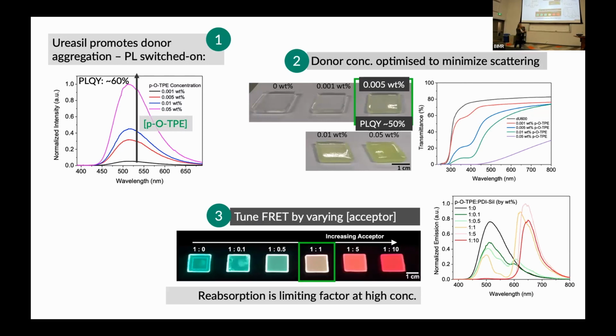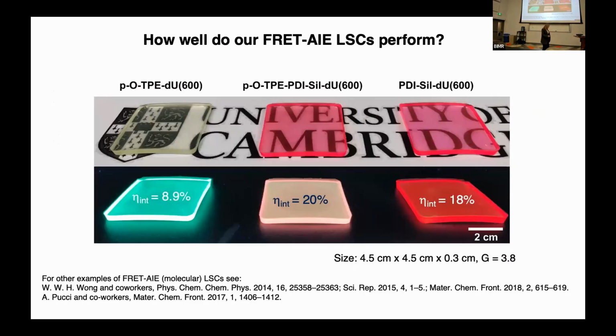So coincidentally, we found that a 1-to-1 ratio of the donor to acceptor worked best. That was just how it worked out. So what we did is we made big LSCs, and we looked at the internal efficiency of the LSCs.